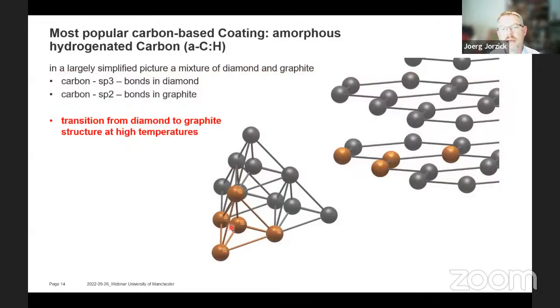One important thing to point out for the diamond-like carbon coatings is this temperature limit and the graphitization, where the very stable diamond structure is converting into the graphite structure. And this goes with temperature and also depends on the actual application pressure. And that is basically one of the reasons why the application is limited in temperature for the carbon-based coatings.